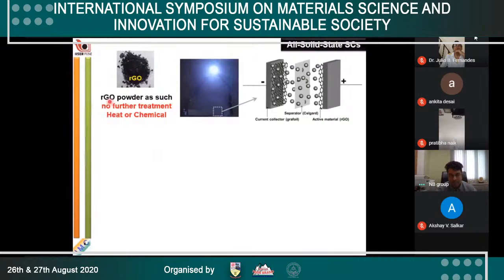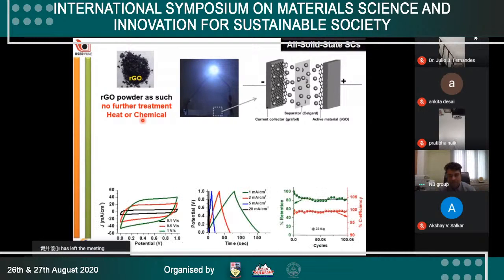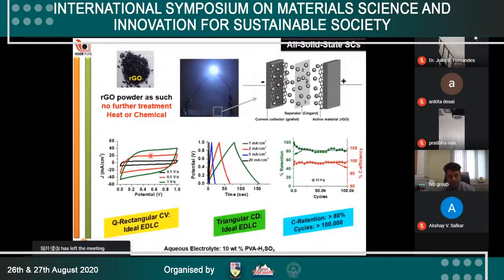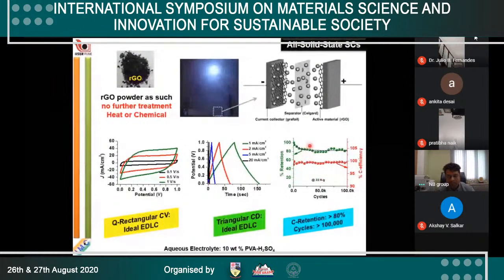We have used RGO powder as such and assembled all solid-state supercapacitor. RGO powder as such means no further treatment, heat or chemical. Please remember, any such treatments cost additional energy and we should avoid. Here are the electrochemical performances: cyclic voltammogram, charge discharge cycle, cycling stability. No Faradaic peak could be observed in the cyclic voltammogram so as charge discharge cycle. We could go beyond 100,000, 1 lakh charge discharge cycle at such a high current density. And what we have observed, more than 80% retention of the capacitance, which is remarkable.